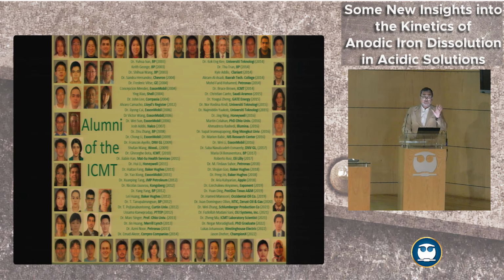We said, all right, we're going to try to use the best possible electrochemical technique that looks at the mechanisms, which is electrochemical impedance spectroscopy, which I'm going to bombard you with a few slides on in a second. And then I was very lucky to be able to use TOF-SIMS as a completely different technique to try to verify some of the results. And you will see that's the subject of today's talk.